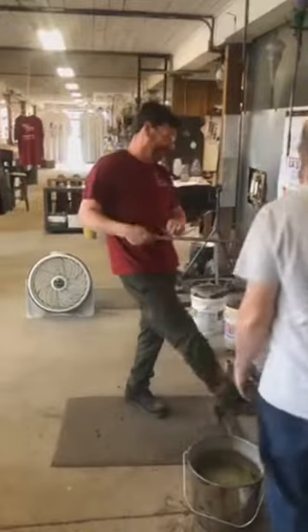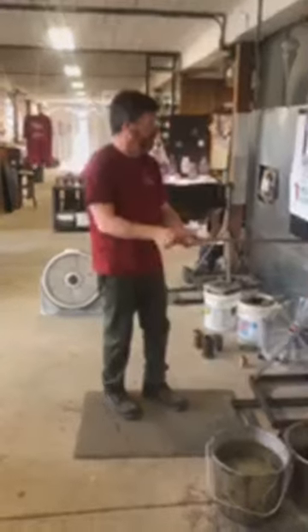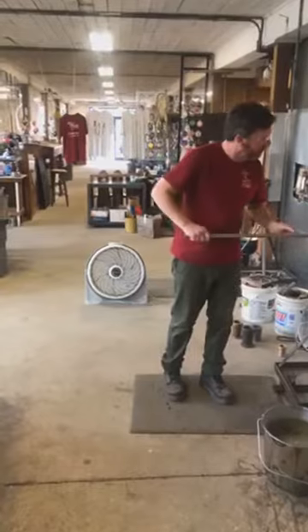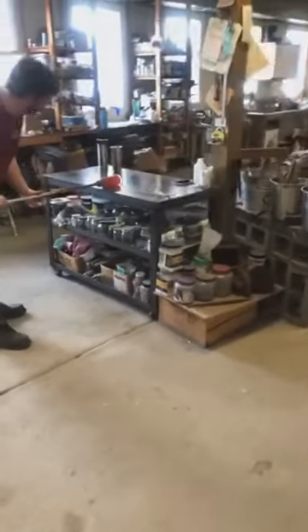Okay, so if we close everything down and just use the glass where the Murini is, you can lose a lot of the Murini. So by adding a little bit of clear, we have different ways of doing this. We can put strips of glass on the bottom. We can create a plug for the entire bottom. You saw Todd put a wrap on there.